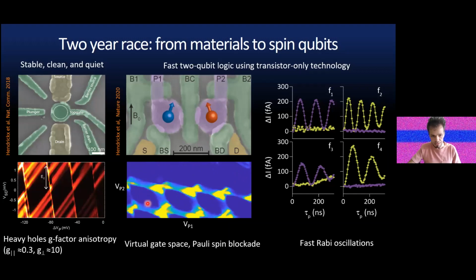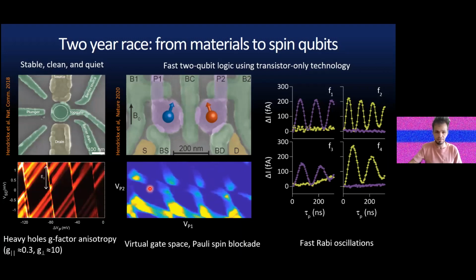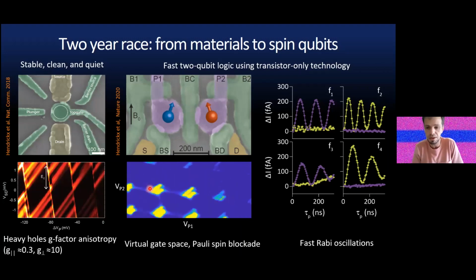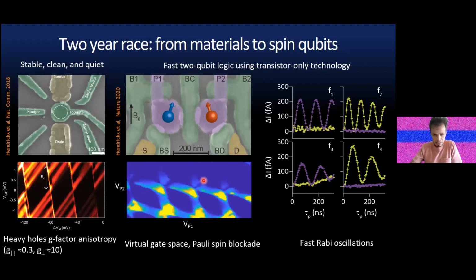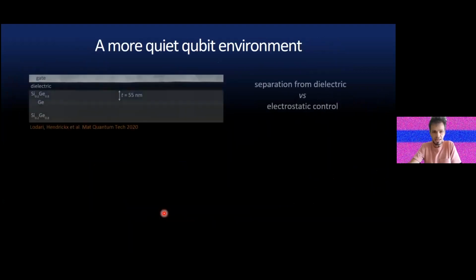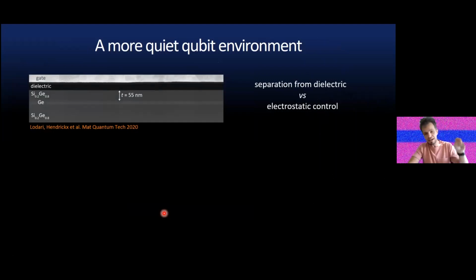Here is also nice control. By moving the barriers, if you change the coupling, you can go from a two quantum dot system to a single quantum dot. Again, this put the platform under the radar of the community. But then we were not really satisfied from a materials perspective, because we knew the percolation density wasn't the best we could get. And so here comes in a nice feedback loop on the materials which I want to highlight.